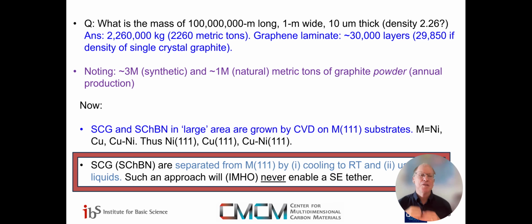So we currently can make single crystal graphene and single crystal HBN. We can grow them epitaxially on certain metal 111 substrates, nickel, copper, copper, nickel. And the same for single crystal HBN, including several layer. We can grow, as our group has in collaboration with Professor Hyun-Suk Shin, on nickel 111, and I'll show the publications later. And then we'll also see that there are possibilities about growing on liquids, like liquid copper.